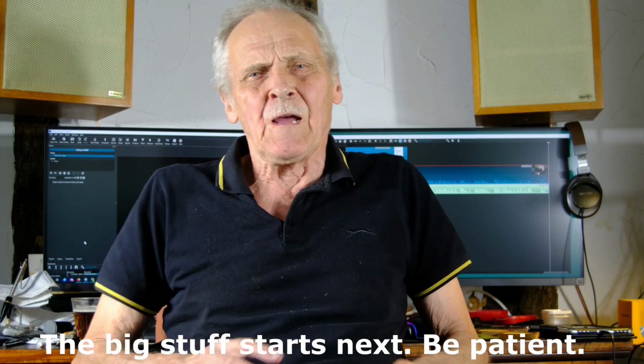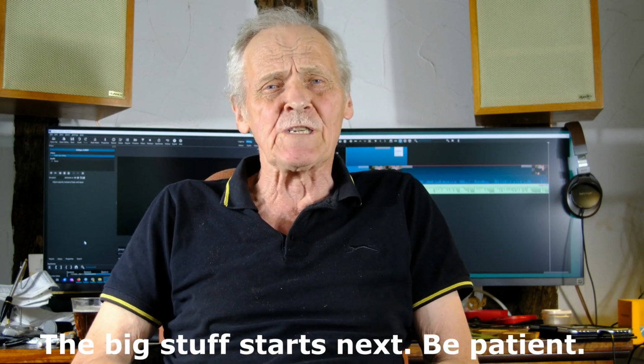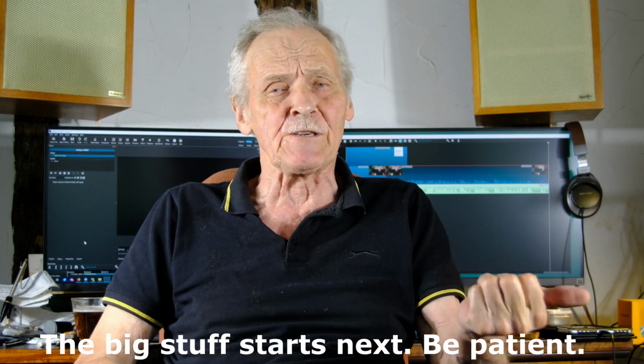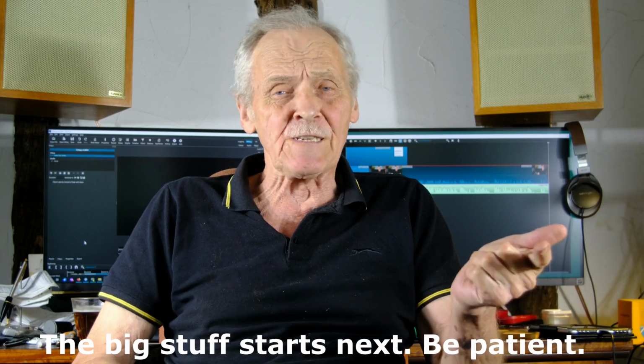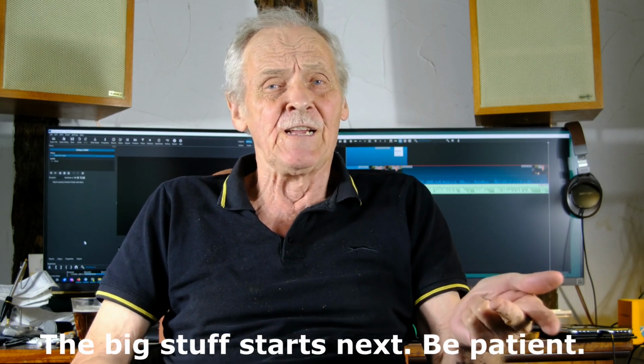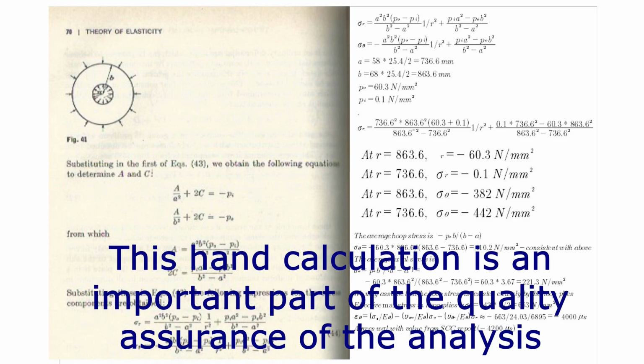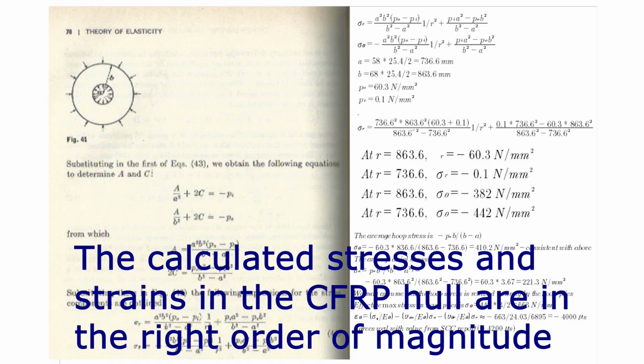Not good. And whilst on the subject of quality assurance, it would help if they showed displaced shape plots, if they reported stresses rather than strains, and if they reported the support reactions. It would make it much easier to verify the results. However, my little hand calc here predicts maximum strains on the inner surface of 4,000 microstrains compared to their number of 4,200, and on that basis I'm not worried that there are any basic errors.